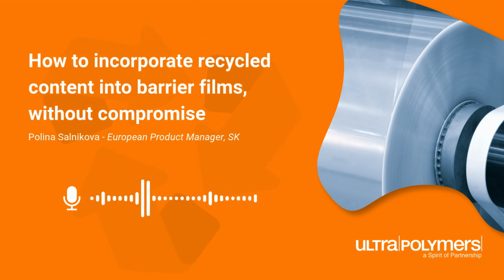Conclusion. The key learning from the project was the importance of compatibilization. In multi-layer systems, even monomaterial films, where all layers are from the same polymer family, incompatibilities can arise when incorporating recycled content. Therefore, without intervention, recycled blends suffer from poor morphology and weak interfaces. This case study shows how compatibility can be achieved in one simple step, and that recycled content can be integrated into high-performance films without sacrificing quality or efficiency.